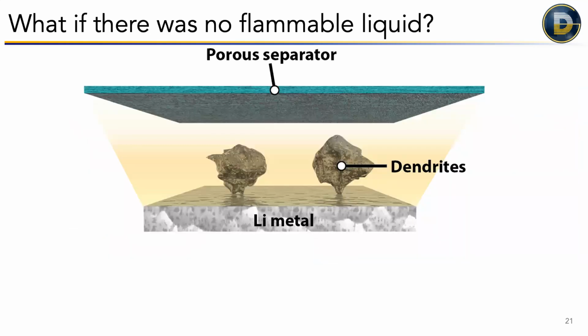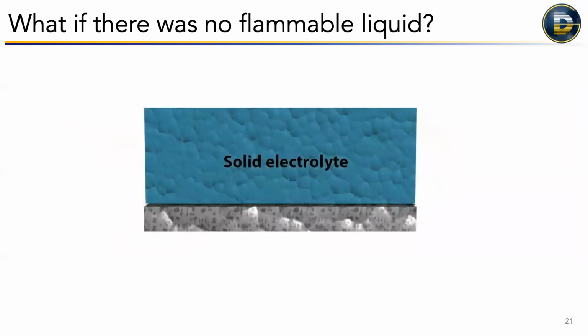But what if we could replace that liquid electrolyte and that porous separator with a solid material that was non-flammable? This would be great, right? But that solid material would have to do everything that the liquid does and the porous separator does, namely conducting lithium ions very, very quickly, not allowing electrons to go through, and to physically block the two electrodes from touching each other, all while being safe and stable for thousands of cycles and all of this.